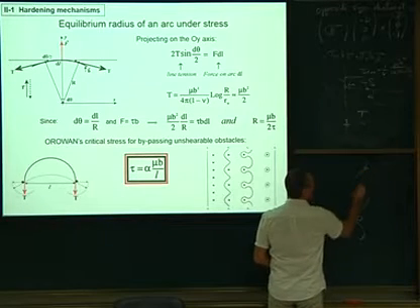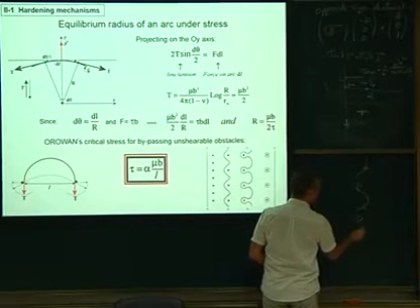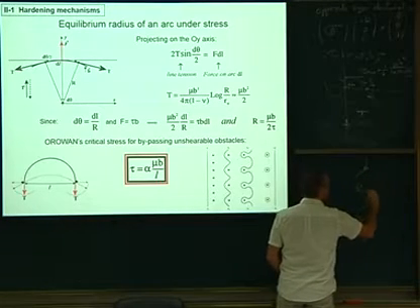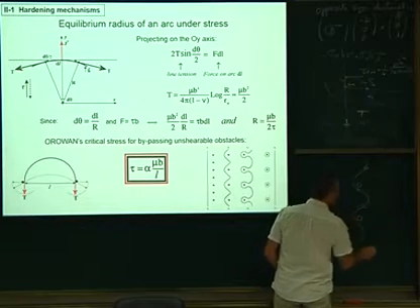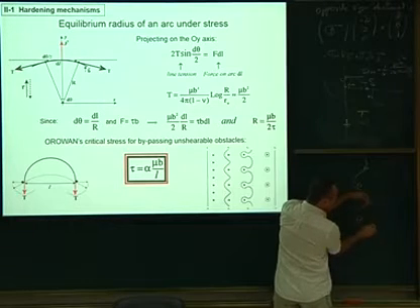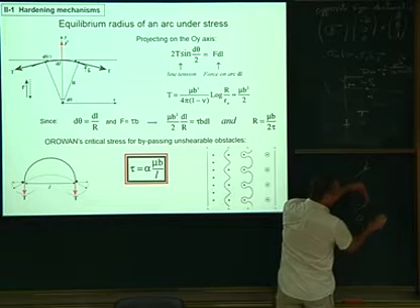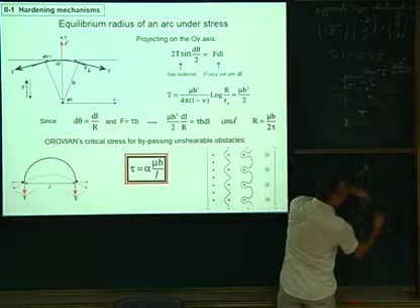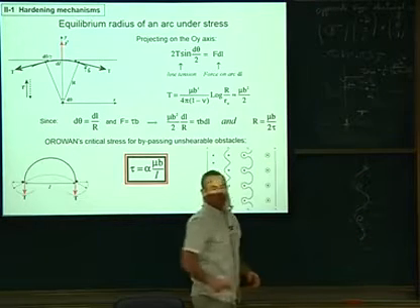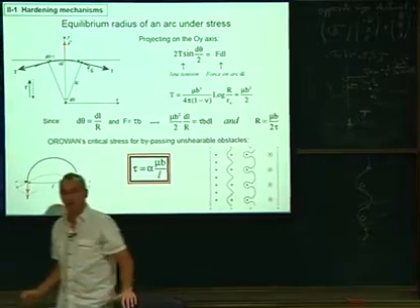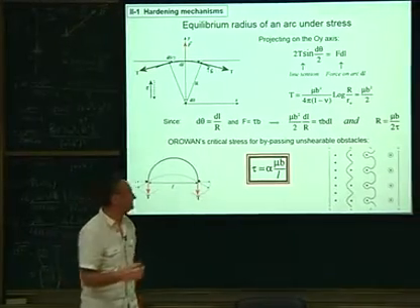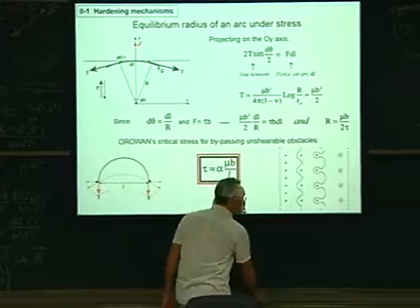If you put some line orientation on your dislocation, of course, at a given point, this will bow out like this, and you have this orientation and the opposite. So when those two merge, they will annihilate, leaving some dislocation away. Okay? And then you have a residual loop, which is surrounding your obstacle. This is called the Orowan loop. This loop is an Orowan loop. Okay? So this is the mechanism.